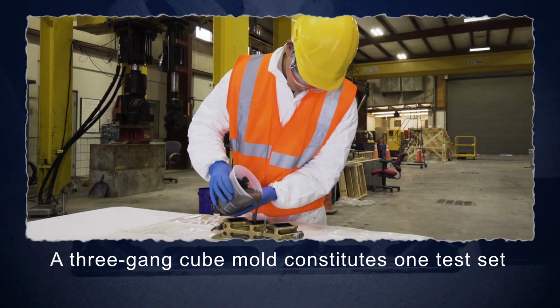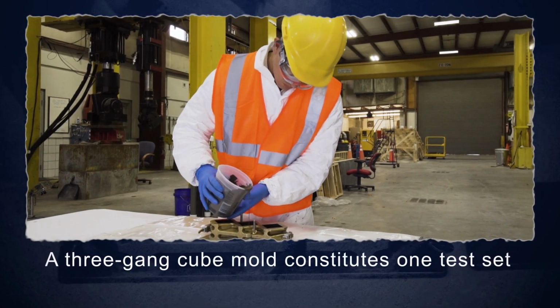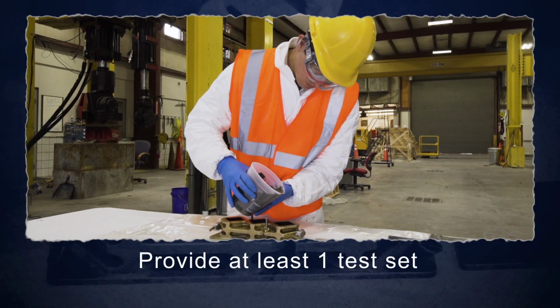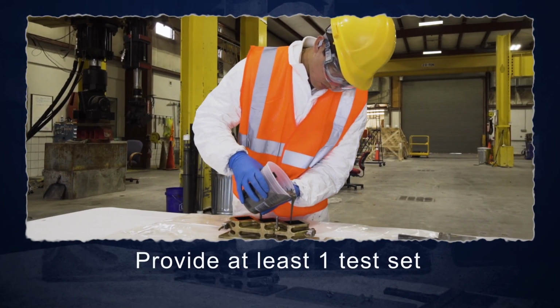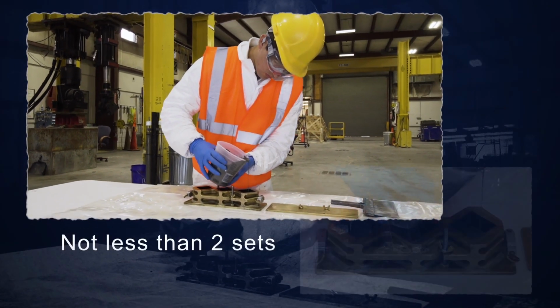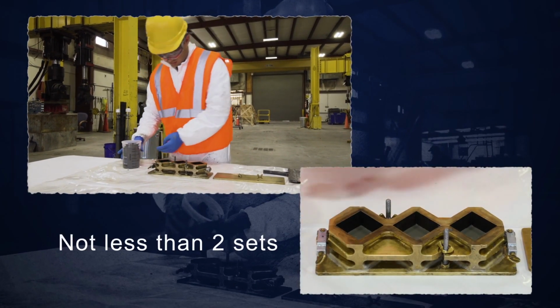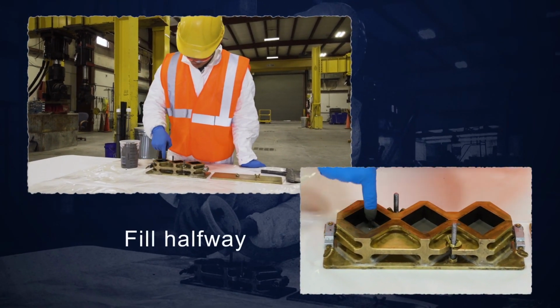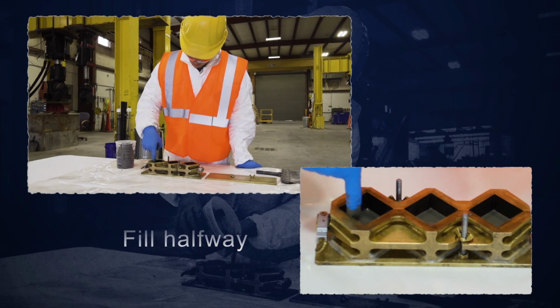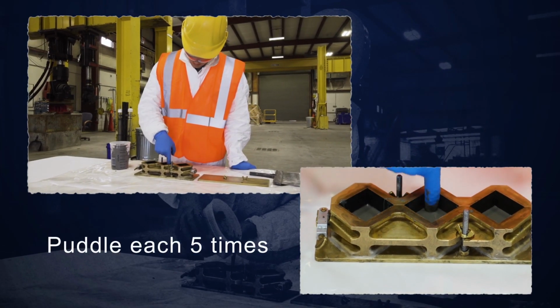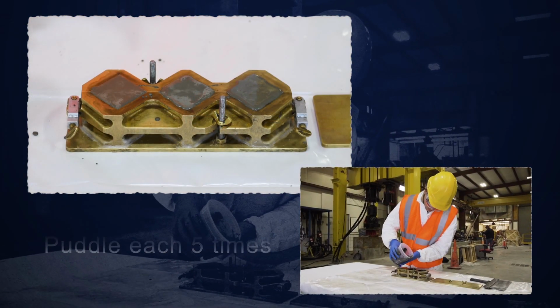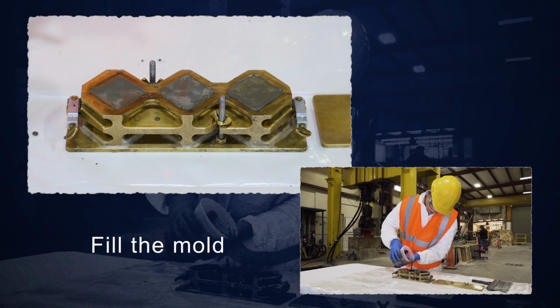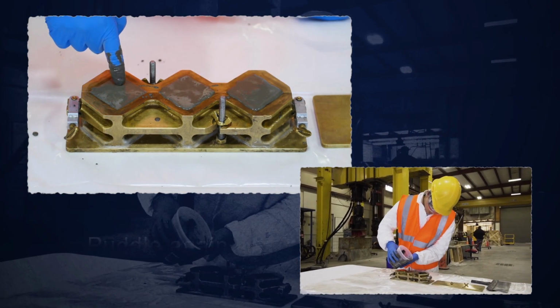A 3-gang cube mold constitutes 1 test set. Provide at least 1 test set for each age at which strength is to be determined, but not less than 2 sets. Fill each mold in the set halfway. Puddle each with a gloved finger 5 times to release entrapped air. Fill the mold and puddle again.